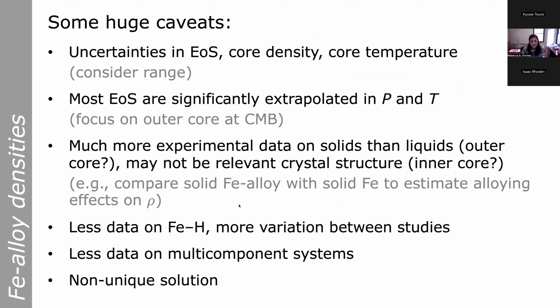Most of the equations of state I showed on previous slides are significantly extrapolated in pressure and temperature. That is why we often focus the calculation on how to match the density at the CMB, assuming there are no thermal boundary layers there. We have a lot more experimental data on solids than we do on liquids, just because of limitations in the kinds of measurements we can make, which makes it harder to make comparisons to the outer core. There's certainly not no data on liquids. There's certainly some shock data at these pressures, for example, which I am not going to go into today.